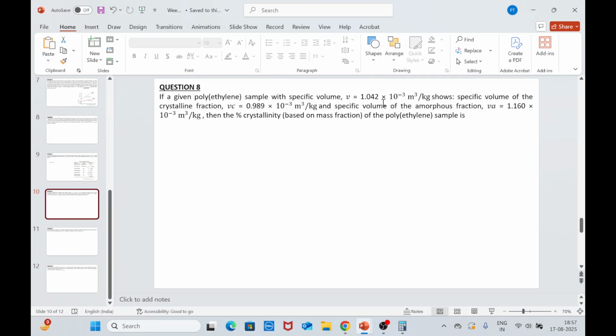You are given a polyethylene sample with a specific volume of 1.042 times 10 to the power minus 3 meter cube per kg. The specific volumes of the crystalline fraction and the amorphous region are given, and they are asking you to calculate the percentage crystallinity. This particular polymer shows a specific volume for the crystalline fraction as 0.989 times 10 to the power minus 3 meter cube per kg, and the amorphous fraction shows a specific volume of about 1.160 times 10 to the power minus 3 meter cube per kg. Based on this data, you are supposed to calculate the percentage of crystallinity.